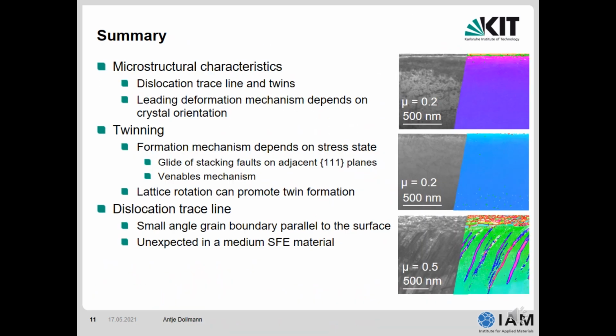Summing this up, we have seen different microstructural characteristics, which are the dislocation trace line and the twins. And it seems like the leading deformation mechanism depends on the crystal orientation. For the twinning mechanism, we have seen two different formation mechanisms. On the one side, the glide of stacking faults on neighboring 111 planes, and on the other side, the Venables mechanism. And it seems like lattice rotation can promote the twin formation.